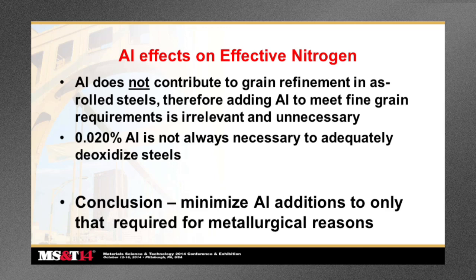And also we know that a minimum aluminum, say 0.020, is not always necessary to adequately deoxidize steels. In fact, the vanadium nitrogen system is widely used in the long product arena, where it typically is silicon killed and no aluminum is added. So we know you can cast steels with lower levels of aluminum than 0.020, or perhaps what has traditionally been accepted throughout the industry today.